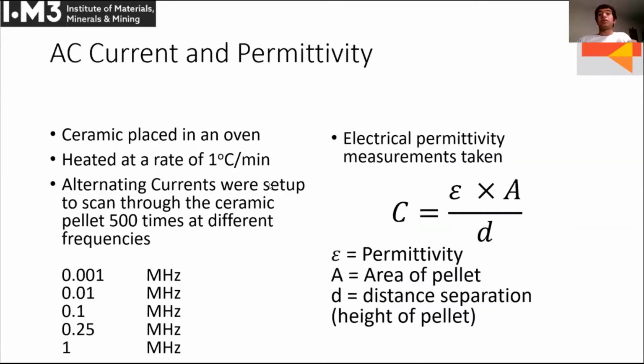So then how we measure the electrical response is we put the ceramic in an oven and heat that oven at a rate of 1 degree per minute. And then we set up alternating currents, which just go from one direction to the next, kind of reversing direction.